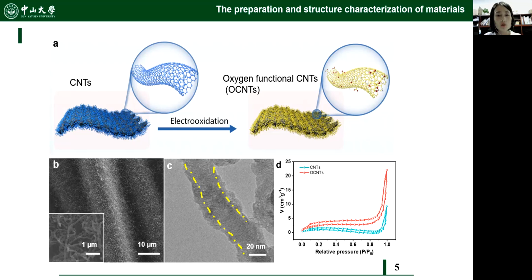The BET analysis also verifies that the specific surface area of OCNTs on carbon cloth is remarkably larger than that of the CNTs, meaning that the specific surface area of CNTs can be dramatically increased upon the electrochemical oxidation process.